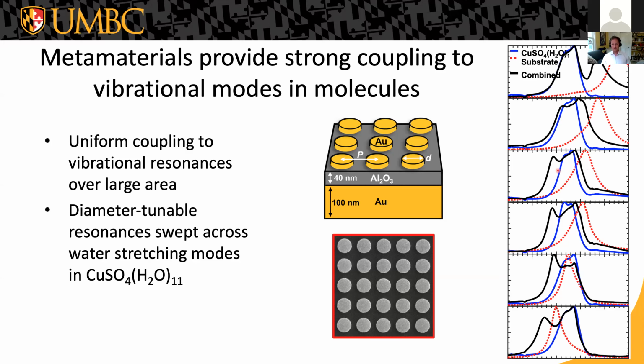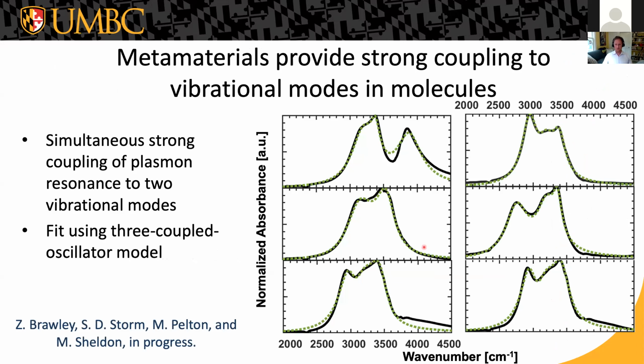simultaneously. So if we try to fit this to a 2-oscillator model, we can't reproduce the experimental results, but we can get very good fitting with a 3-coupled oscillator model. Interestingly, it's inducing an effective interaction between these vibrational modes that were previously uncoupled or very weakly coupled anharmonically within the water molecule. Now, since they both couple to the same plasmonic mode, there's indirect energy exchange between the 2 of them, and maybe with some implications, say, for polaritonic chemistry.